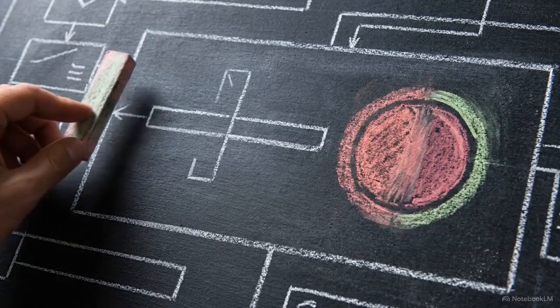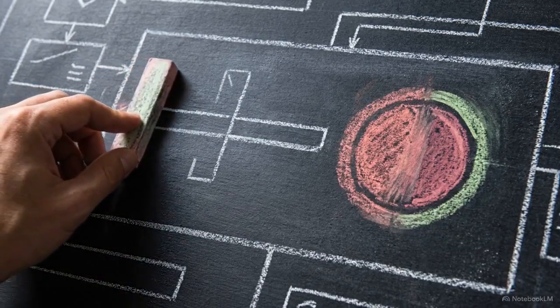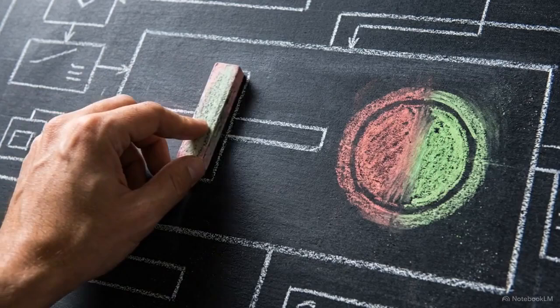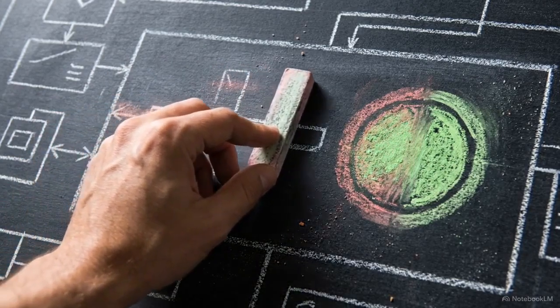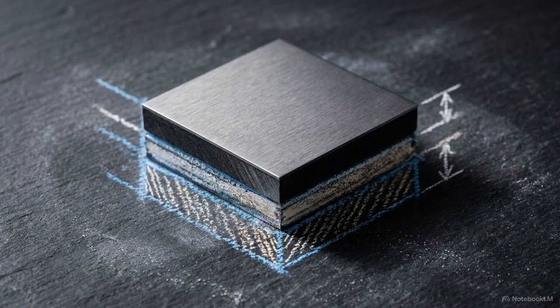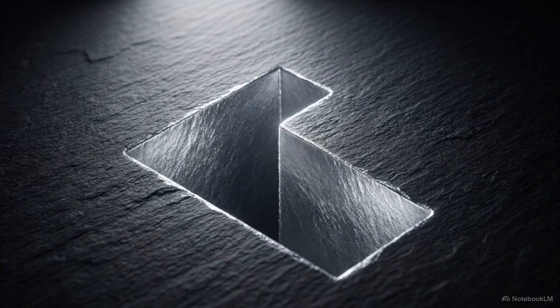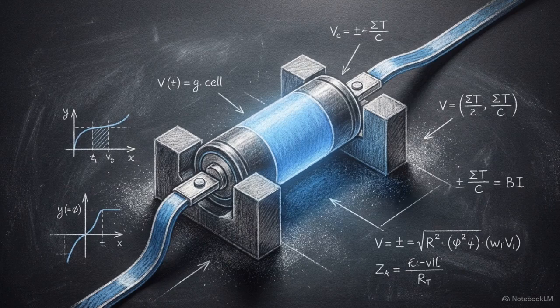The exact parameters for that proper cutting region are not static. The optimal window shifts entirely depending on whether the electrode is compressed. Generating a clean cut requires calibrating the volume energy directly to the structural density and thickness of the specific electrode. Manufacturing a clean edge is only part of the equation. We have to track how these structural decisions impact the long-term electrochemical performance of the cell over multiple charge cycles.